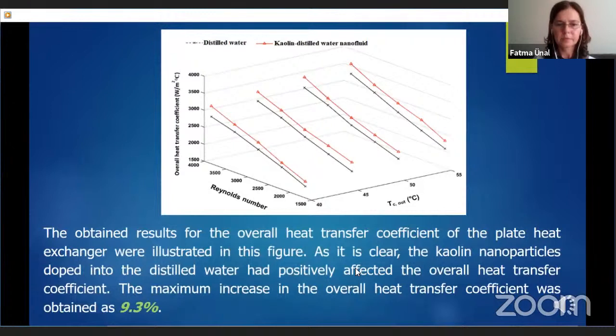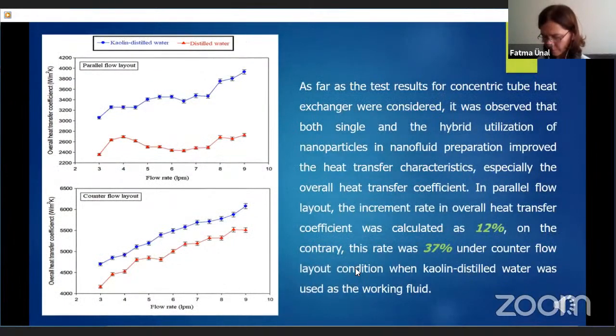Regarding the obtained results from the experiments, it is seen that the kaolin nanoparticles doped into the distilled water had positively affected the overall heat transfer coefficient. The maximum increase in the overall heat transfer coefficient was obtained as 9.3%. As far as the test results for the concentric tube heat exchanger were considered, it was observed that both single and hybrid utilization of nanoparticles in nanofluid preparation process improved the heat transfer characteristics, specifically the overall heat transfer coefficient, as you can see in these figures.